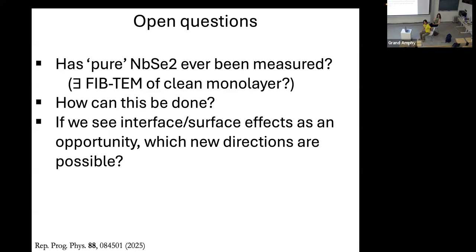Because there's this whole question of whether NbSe2, being a quasi-2D material, has a CDW that comes from Fermi surface nesting, unlike other materials such as quasi-1D materials like NbS3, where it's clear it's nesting. But NbSe2 had this long debate over whether it was nesting or not. And this paper seemed to have settled it at that time, that they found some evidence for nesting behavior. And they also found evidence for nesting, you're saying? Yes, the Fermi surface nesting. They claim to have found some signatures, and apparently there were some signatures of CDW even above TC. This is for bulk. Above the TC of 33 Kelvin.